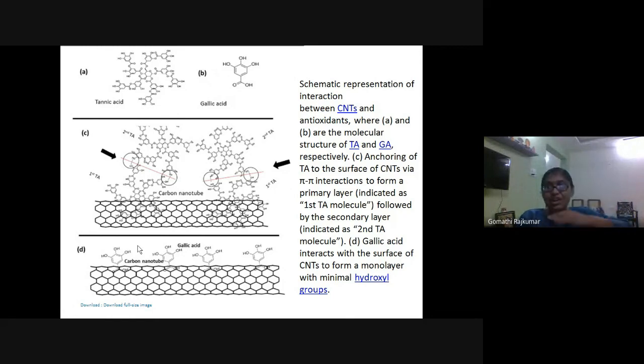Therefore, it was like first layer of tannic acid followed by second layer of tannic acid, whereas gallic acid was only a mini monolayer with minimal hydroxyl group. When it was second layer, it did exist. Friends, I will tell you, there was a second layer, but the second layer was not stable. Only in case of tannic acid, the second layer was stable. Whereas in case of gallic acid, the second layer was not stable. Therefore, with gallic acid, we found it to be a monolayer, a single layer coating that was strong. Whereas with tannic acid, we found that 2 layers of tannic acid were very strong. So this was actually the functionalization that we used with carbon nanotubes.